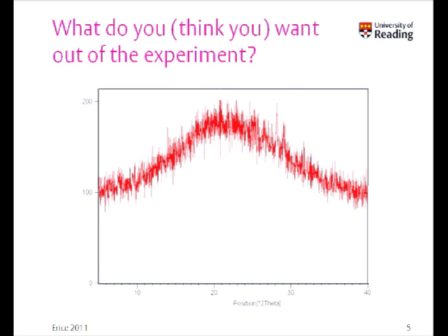And it would be a brave man or woman who said that they could spot any crystalline peaks in there. There's maybe a hint of something slightly sharper, just a touch above the noise level. But the point was that when we asked how long he'd collected the data for, it was about 30 seconds. It was a hyper-quick scan because he did not expect it to be anything other than an amorphous mixture, and so his data collection strategy reinforced that. So we can't actually tell anything really worthwhile out of this.